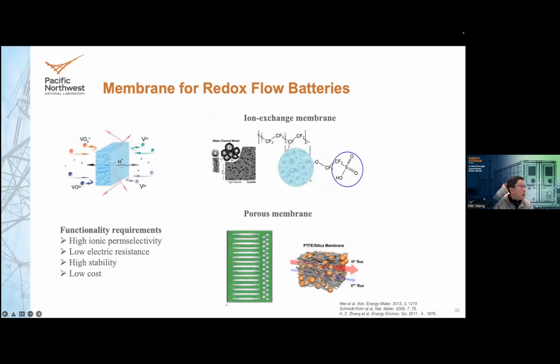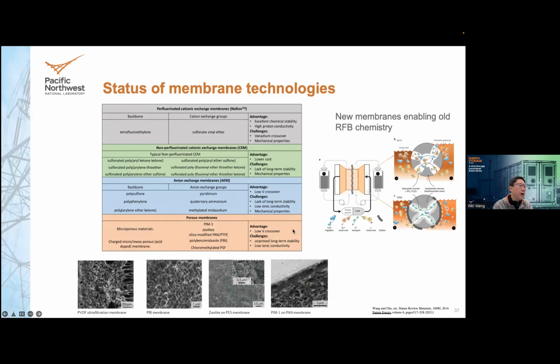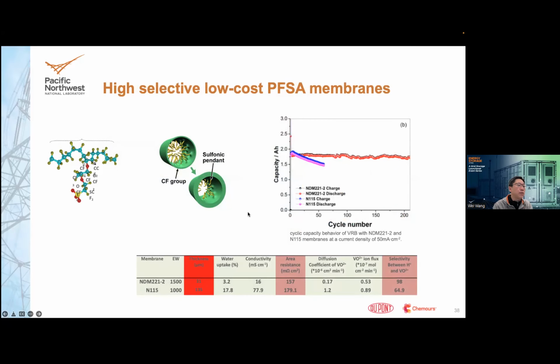And a little bit of membrane study. Actually, I consider membrane one of the most under-investigated areas. A lot of phenomena in the flow battery are related to the membrane, which primarily functions as a separator that needs to provide high ionic conductivity and also selectivity. So it's many times two opposite properties. Some of the research was geared towards minimizing the pore size to increase selectivity, like some of the work we did to tailor the pore size to increase selectivity, while also increasing the backbone's hydrophilicity to increase the conductivity.